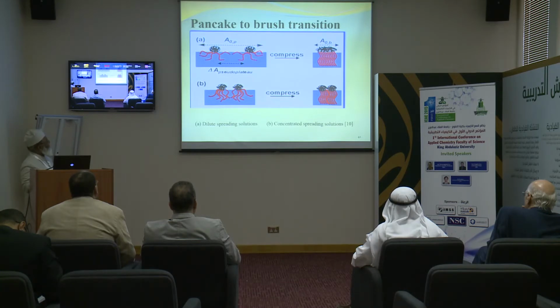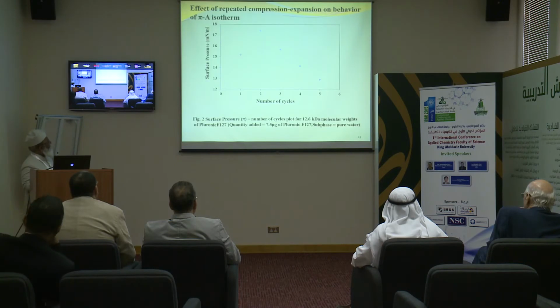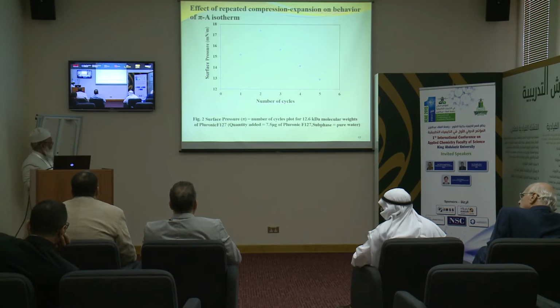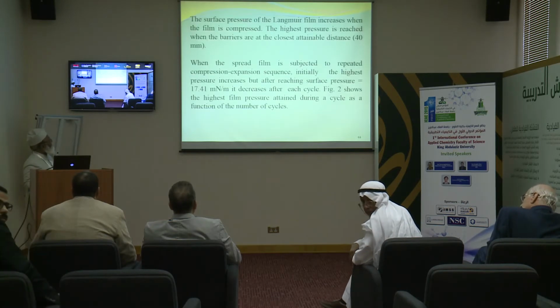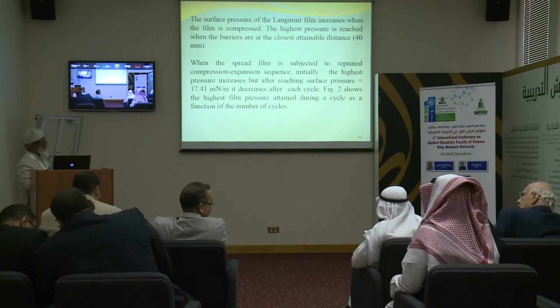This is a diagram showing the pancake to brush transition for dilute spreading solution as well as for concentrated solution. This diagram shows the effect of the surface pressure versus the number of cycles plot for 12.6 kilodalton molecular weight Pluronic, and the subphase was water. When the spread film is subjected to repeated compression-expansion sequence, we got the highest pressure that increases after reaching the surface pressure of 17.4.